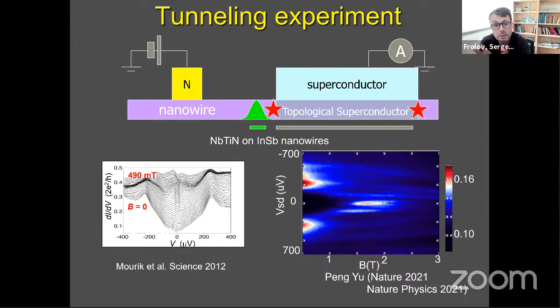Yeah, so there are several reasons, in fact. Yes, I only spoke about G factor, and I also mentioned spin orbit interaction being strong. So it's indium and antimony are heavier elements, so the band gap is smaller. It means large spin orbit and large G factor. But another consequence of small band gap is the electrons are light, effective mass is low, and mobility is high. So in a reasonable size wire, like 100 nanometers, which we can handle with nanofabrication very nicely, electrons occupy the whole cross section. So the de Broglie wavelength, let's say, of these electrons is larger. So they are more quantum, sort of, at reasonable size systems. So we don't have to fabricate one atom thick wires. It can be 100 atoms across.